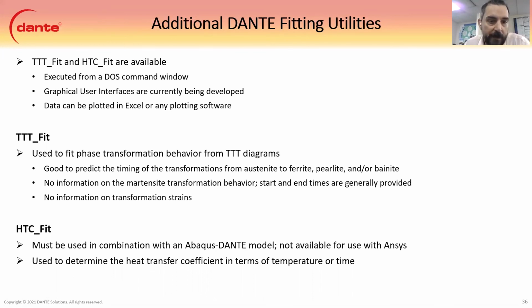The HTC fit is another one that's pretty powerful, actually, but you need to use an Abaqus DANTE model in order to combine it. Right now, it's currently not available for ANSYS. Maybe in the future we can write a little more to it, but it's used to determine heat transfer coefficients from time-temperature data, so your thermocouple data, or model data or something like that. You can determine what HTC, heat transfer coefficient, was used on the surface of the part, and it works really well as far as fitting those HTCs.